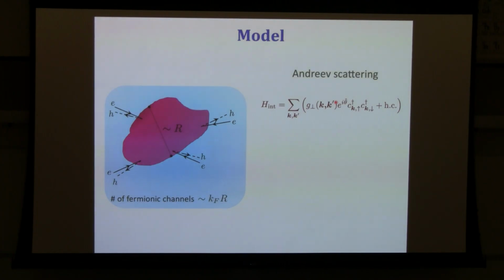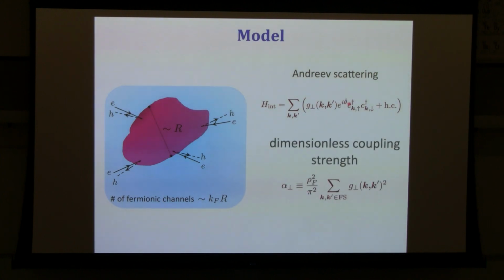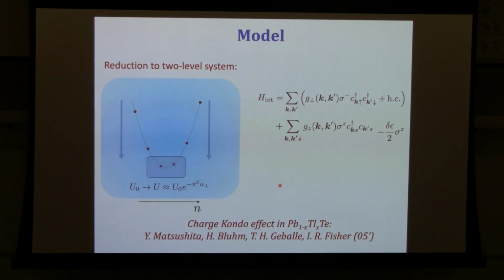Basically, that's the scattering amplitude of an incoming electron with some momentum into an outgoing hole, in this case with some other momentum. I didn't write it here, but there's also a normal reflection that turns out to be less important when you analyze this problem, but it's also there in our modeling. It's convenient to characterize this by a single number. In principle, there's a whole coupling function here, but there's a dimensionless number which is useful, the dimensionless coupling in the Andreev channel, alpha perp. So that's the coupling strength.